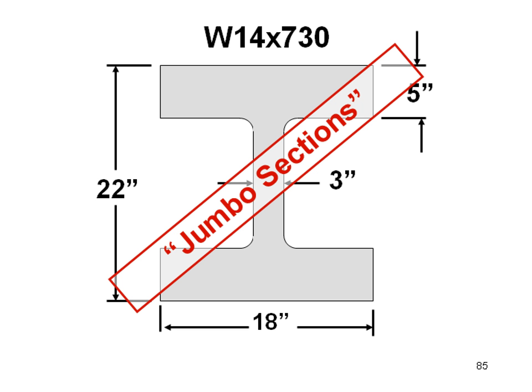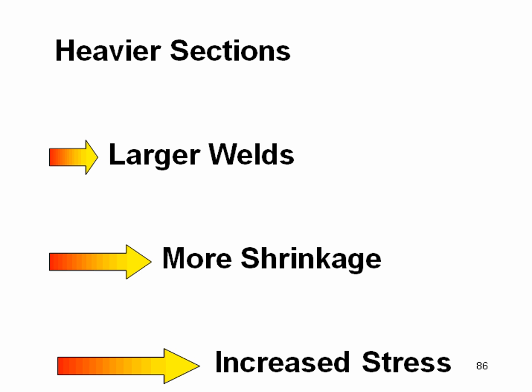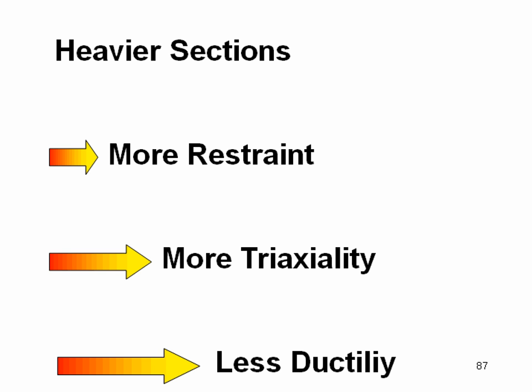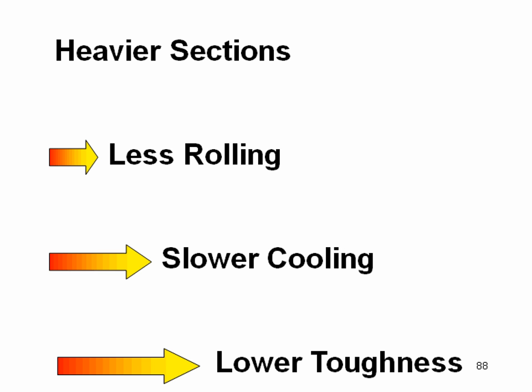Now, when we start welding on these heavier sections, what happens? Well, we start making larger welds. Larger welds have more shrinkage. The increased shrinkage means we're going to have more residual stress in these connections. Heavier sections also are more highly restrained. The higher restraint is going to create more triaxiality, and as we're going to see, the more triaxiality leads to less ductility. And finally, as I'm dealing with heavier shapes, the materials themselves change.